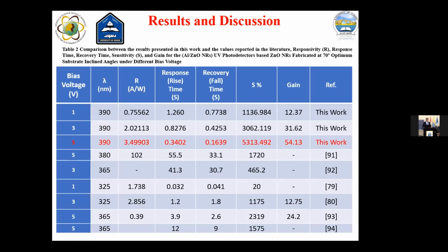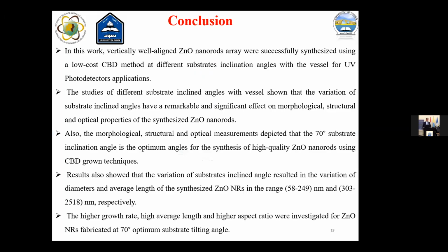In the last conclusion, in this work, vertically well-aligned zinc oxide nanorods were successfully fabricated using the low-cost CBD at different substrate inclined angles for UV photodetector application. The study of the different substrate inclined angles showed that the variation of the substrate inclined angle has a remarkable and significant effect on the morphological structure and optical properties of the zinc oxide nanorod. Also, the morphological structure and optical measurements show that the 70-degree substrate inclined angle is the optimum angle for the UV photodetector for high quality.